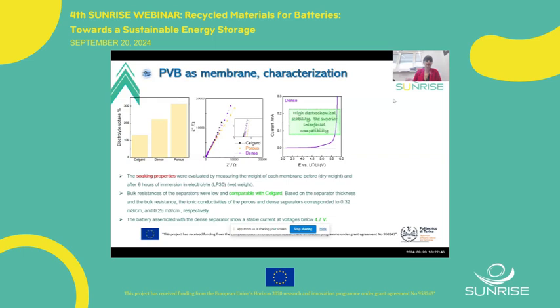As we can see, regarding the uptake test, the prepared membrane with PVB shows even higher uptake than the Celgard membrane. Regarding ionic conductivity, characterized by impedance, both porous and dense membranes show ionic conductivity comparable with Celgard.